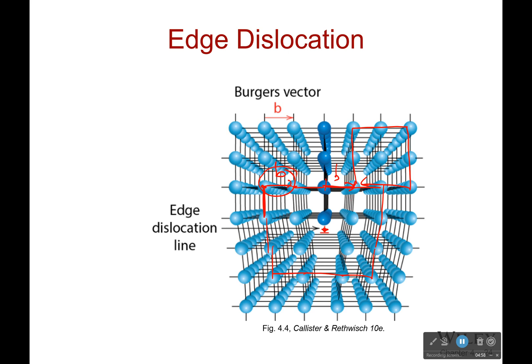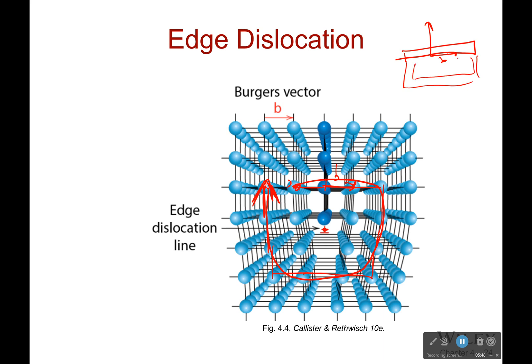Now, what I said earlier is that this is perpendicular to my dislocation line. That's a little bit harder to see until you remember that right hand rule. So what you're going to do is take your hands - we have a nice little spiral right here caused by my dislocation line, going in this direction. Curve your hand around this. Remember, your pointer finger is where the arrowhead is, and the base of your hand is where the tail is. Now, what direction is your thumb pointing? If you're using your right hand, it should be pointing straight into your computer screen. So now let's look at it from above: here's the Burgers vector B on your computer screen, and your thumb was pointing into the computer screen. These are going to be at right angles to each other - this is perpendicular. It works.